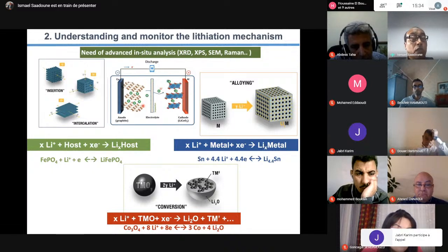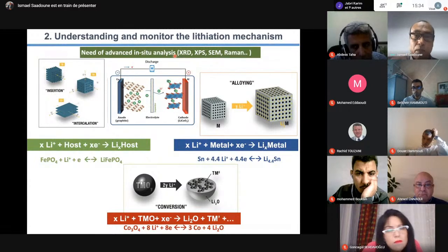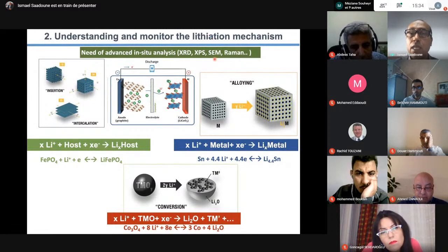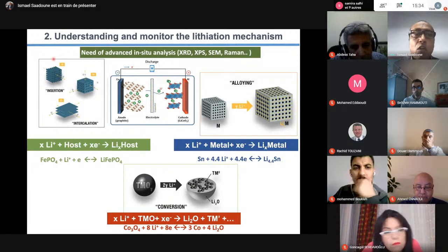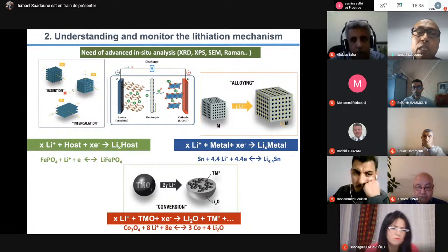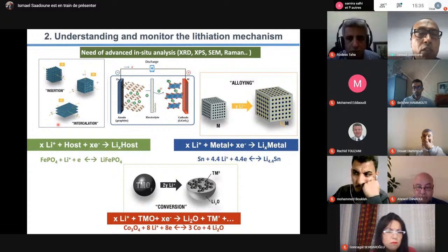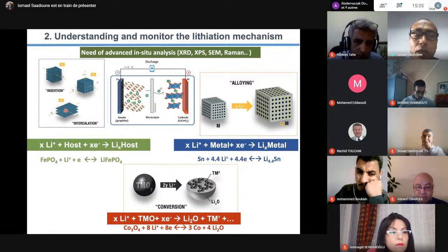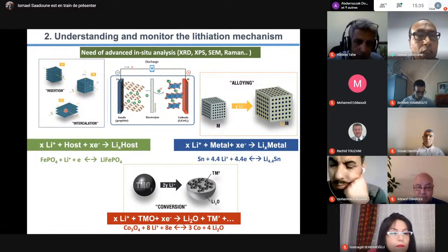So we should keep in mind that we need in situ analysis. In situ means we have your cell and we follow the XRD, XPS, SEM, Raman to see what happens in operando in your cell. But in general, there are 3 mechanisms. The first one is simple lithium insertion - we have a structure, we introduce lithium through some van der Waals bonding, and then we remove it.